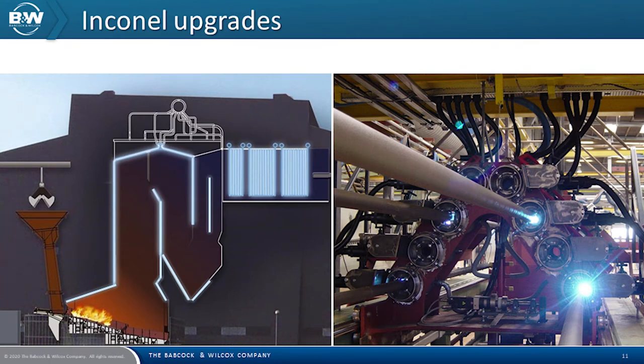A variety of solutions have been developed and used over the years to address lower furnace corrosion. One solution was the Inconel weld overlay. This was pioneered in waste-fired boilers and has gained general acceptance since the early 2000s on the lower furnace walls of large mass-fired boilers. The good corrosion resistance, the high thermal conductivity, the metallurgical bond to the base tubes and membrane bars, and the wear resistance have made Inconel overlay the primary approach for lower furnace corrosion protection in new designs.